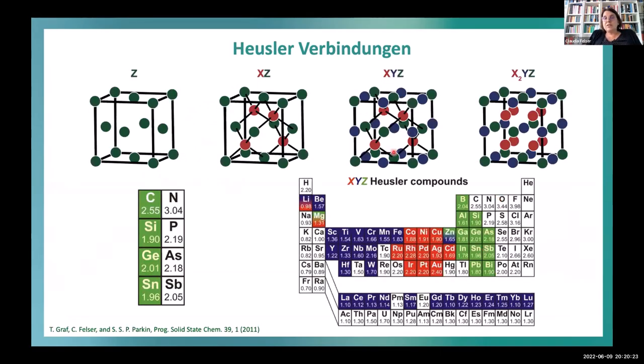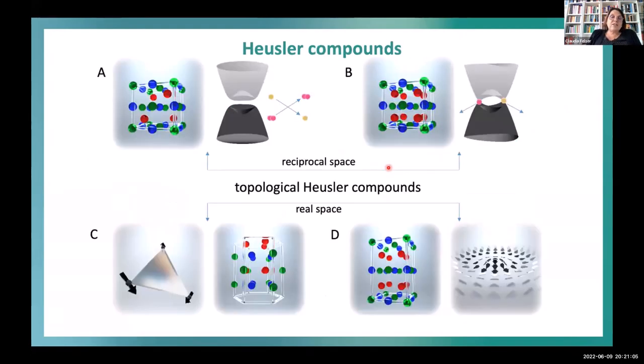So there are two kinds of Heusler compounds. We focus today mainly on the full Heusler compound I already described, with four FCC lattices, X2YZ, but there's also the half-Heusler compound. You see that they are in some sense related to the semiconductors, with this very nice tetrahedral kind of lattice that we have in silicon and gallium arsenide. But here, even in the half-Heusler compounds XYZ, we can make fully magnetic materials. So we don't rely on doping a non-magnetic semiconductor to become magnetic, because here we have, for example, manganese on the blue sites in this material. And half-Heusler compounds are a very nice thing to talk about topology, because we can have topology in the electronic structure.